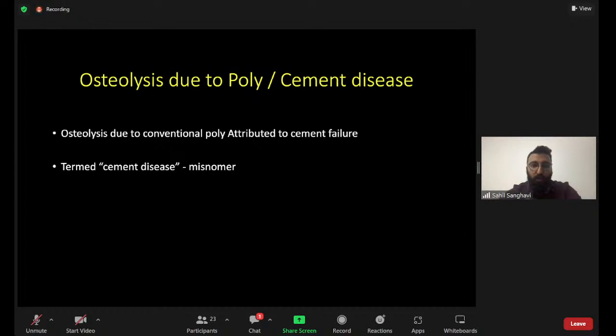However, this osteolysis due to the conventional poly was attributed to cement failure, and it was inappropriately known as cement disease. So cement disease is actually a misnomer wherein the osteolysis was thought to be due to the failure of cement and not due to polyethylene, but it was only discovered later on that polyethylene was the culprit and not cement.